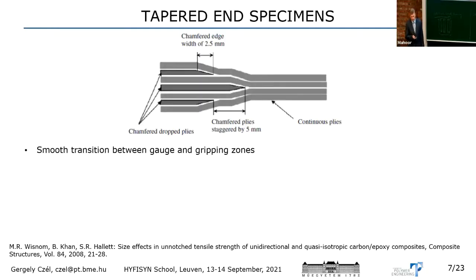So first, let's look at these tapered end specimens. What happens is that there are some plies inserted towards the ends of the specimen to make it thicker. But one key aspect is that they aim at a smooth transition of thickness between the gauge length of the specimen and the clamping region. And a key aspect is that all the plies of the continuous section are kept continuous towards the gripping section. So there are no discontinuities in the plies which are constituting the gauge section of the specimen. And of course, they are continuous on the surface as well.